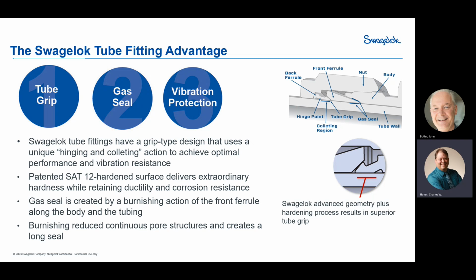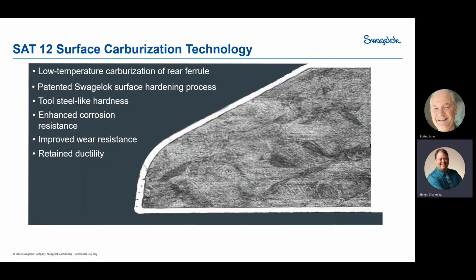And we do the same thing within our tubes. So we hold it right behind that point where we've had the dive into the tubing so that we protect that nose area so it does not become a stress concentration point that would lead to a possible fatigue failure. So that's how we deal with that here. Now, there's a couple other things that come into play that we do. And one of those is what's called SAT12. It's our patented process. It's a low temperature carburization that we do on our rear ferrules.